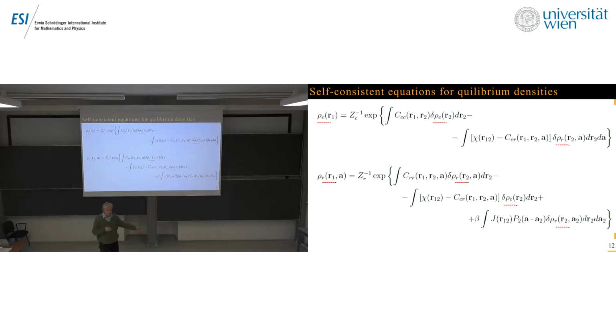But this looks like an effective summation of the infinite series under some assumptions, so what we neglect here are many-body correlations, because we only keep the quadratic term in the expansion of the free energy, and the next term is proportional to the third rank direct correlation function. Well, yeah, this can be important, but still it doesn't change things qualitatively.